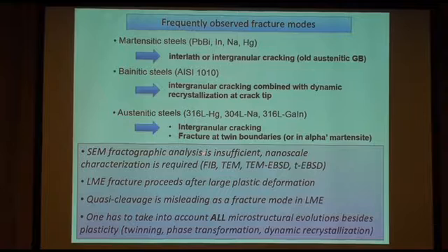So the SEM fractographic analysis is clearly insufficient, and you need to go to the nanoscale to find out about the fracture mechanism, or at least the key fracture path that takes place. And you also need to take into account all the microstructural evolution besides plasticity, and you can imagine the burden of the task of trying to model all that.